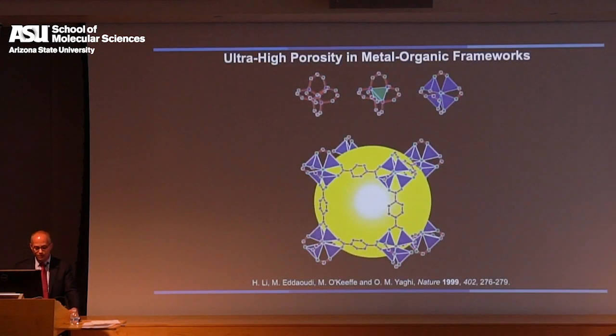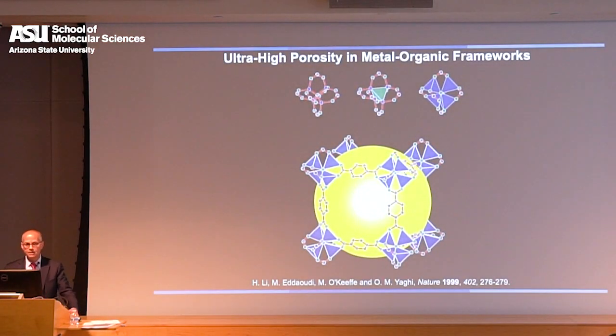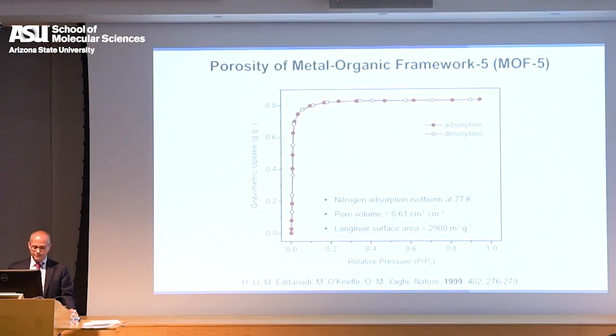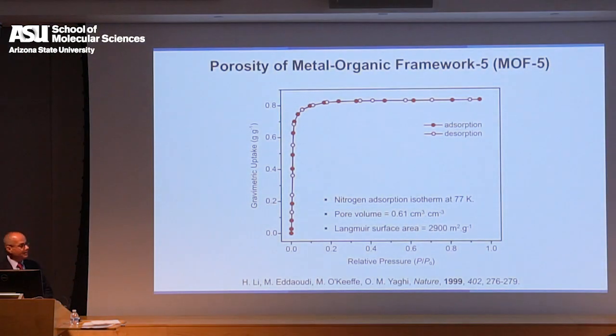That compound was what we called MOF5. So MOF5 was discovered in my lab at Halyan's initiative of linking metal oxide units with organic linkers, or doing the reactions that would produce these metal oxide units. And this was really the true beginning in the eyes of the public or the community of the MOF field, because the surface area, when we measured the gas adsorption isotherm, was so high that when we published this paper, people thought it was a misprint. Surface area is 2,900 meters squared per gram.